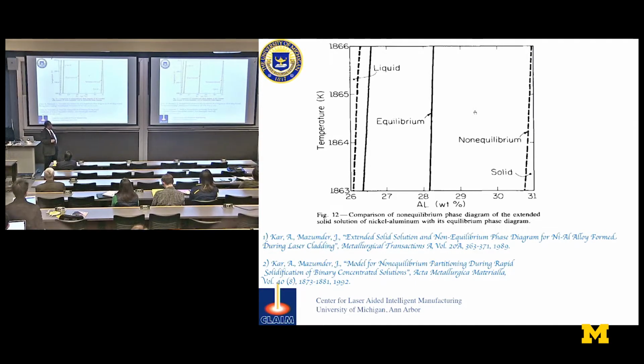We found that whenever you're doing laser melting or laser deposition, your phase diagram changes because of the rapid solidification. It's called atom trapping. There are two formulas. One formula was developed by us, another was by Mike Aziz from Harvard. So we are always competing whose is better, obviously, but this happens. So if this happens, you have to have an online model and find out the composition you are getting instead of what you're starting with. It's never the starting composition, it's a different composition.